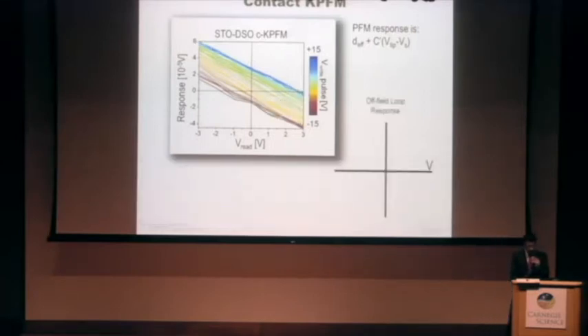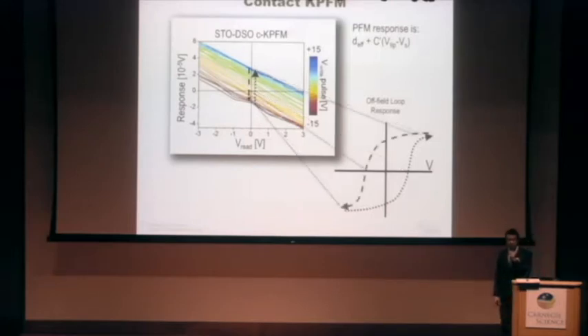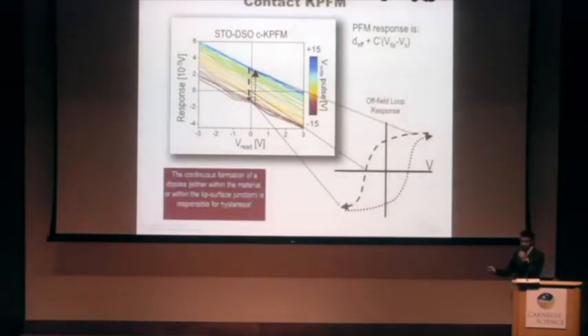Why is this important? Well, if you look along this particular axis here, you will see some bunching, right? Some lines bunching here and some lines bunching here. And so even from a purely electrostatic response, you see this kind of hysteresis loop that occurs. This is interesting and also kind of disheartening, because it means that if you see this ferroelectric hysteresis loop in PFM, it doesn't mean that you have a ferroelectric material. Nonetheless, the important part here is that I want to give you an idea of how to read these particular diagrams. We also think the reason you see this bunching is that you're creating some dipoles, either within the material or within the tip-surface junction, and that's responsible for this type of hysteresis.